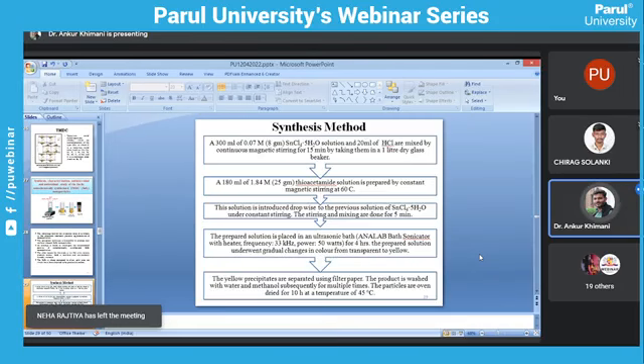So let us see the synthesis of SnS2 nanoparticles. A 300 ml of 0.07 molar, 8 gram SnCl4·5H2O solution and 20 ml of HCl are mixed by continuous magnetic stirring for 15 minutes, taking them in a 1 liter dry glass beaker.